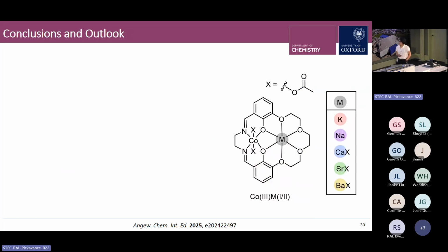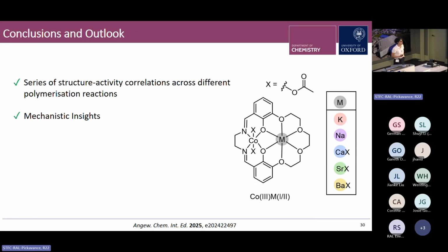So to conclude, I presented a series of structure activity correlations as applied to this series of heterodinuclear cobalt-3 S-block metal catalysts for various different copolymerization reactions. I've also tried to draw out how we can use these structure activity relationships to gain insight into the high performance of the cobalt-potassium combination and the distinct roles of the metals in the polymerization mechanism, and also potentially the balance of the key intermediates in the catalytic cycle and how those might change with reaction conditions.